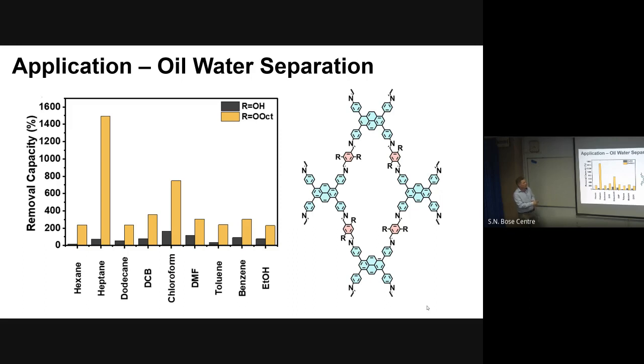We are comparing the non-functionalized material here with the octane functionalized material. You can see that for the hexane, the heptane, the dodecane, we absorb much more of the liquid than in the case of the non-functionalized. We are right now struggling to figure out why the heptane uptake is so much higher. It's difficult to understand how heptane is interacting chemically with this O group, the lone pair of the oxygen. It's completely non-polar. We are thinking that maybe heptane is stabilizing itself better.